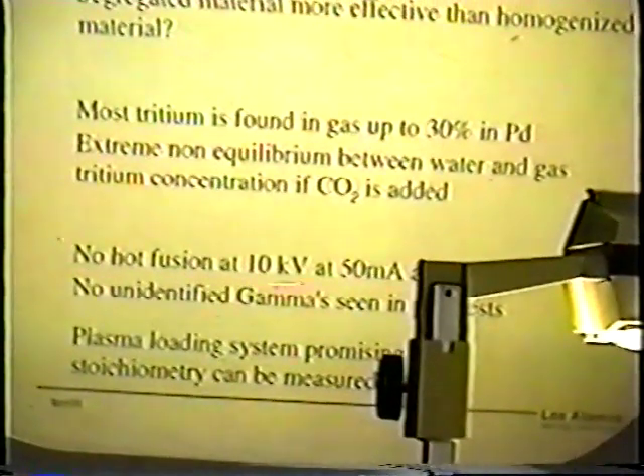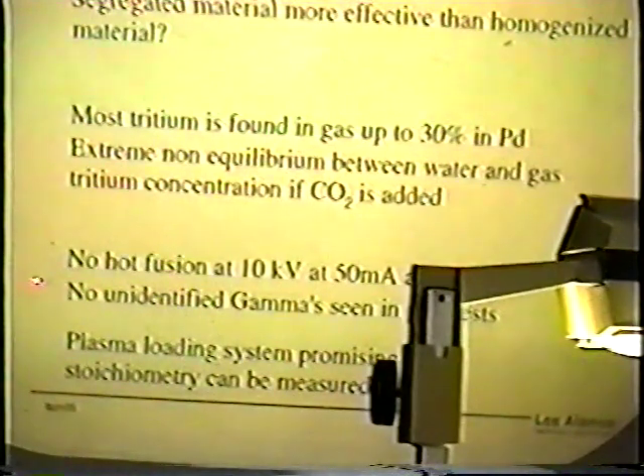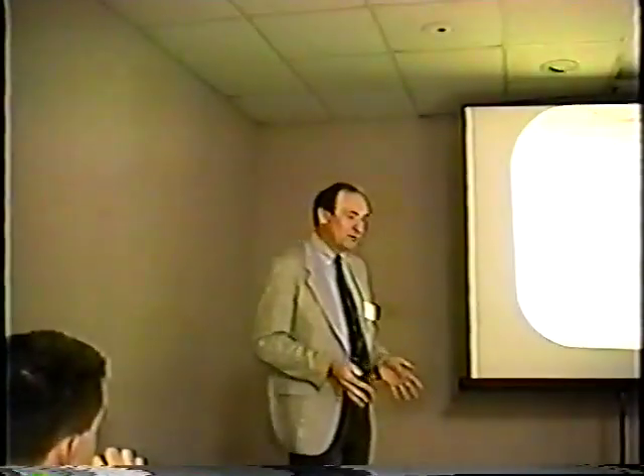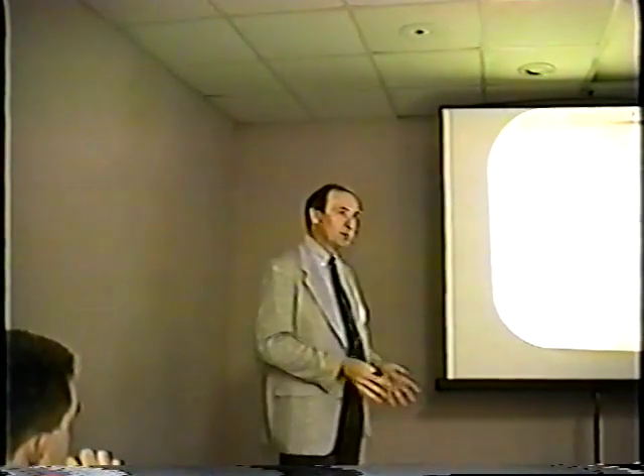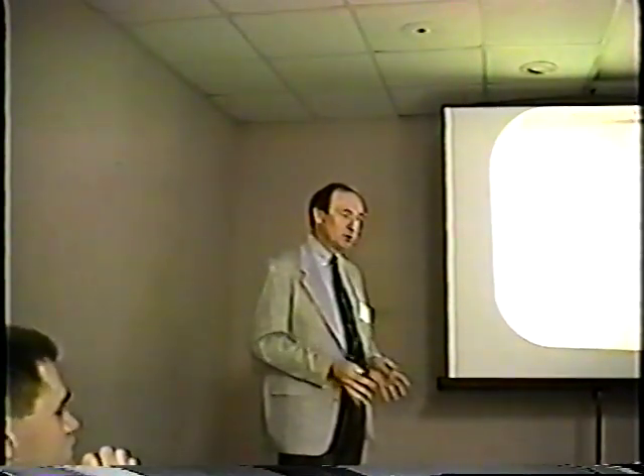When we did that high voltage, low current plasma experiment, we did wheel up a neutron counter to see if we had any neutrons, because we were a little bit concerned about that. And there were no neutrons over the background, and we haven't seen any gammas. So I think what this study is saying is that here's a robust method, if you do everything right, for screening materials. It's very easy to do the experiment.